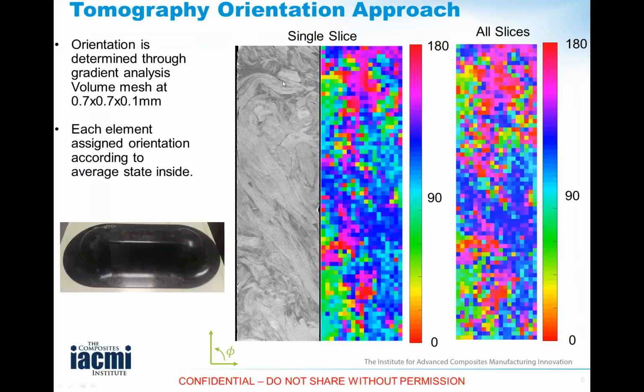So we take that data and then we use a technique called intensity gradient analysis, and fundamentally what that means is, as I'm showing you with my arrow, this is a bundle of carbon fiber or a platelet portion of the fiber in one of the planes.